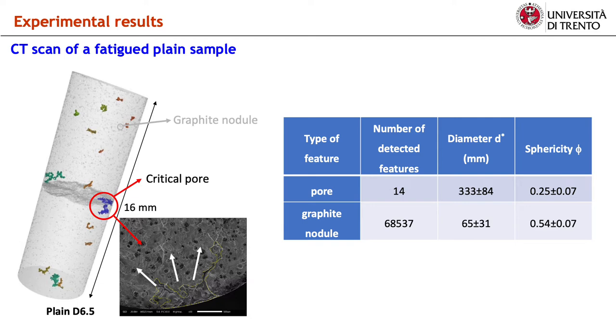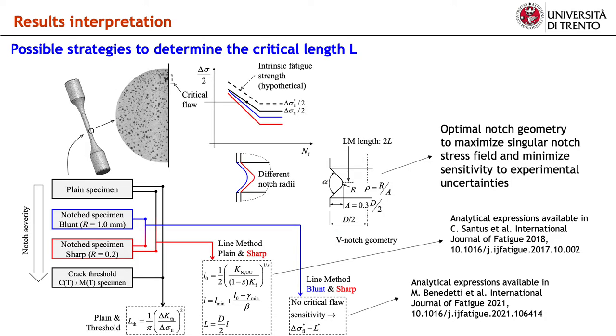It is now clear that the fatigue damage mechanisms prevailing in plain and notched components are different. This could hinder the applicability of the theory of critical distances, which postulates that the critical distance L can be inferred from a plain and a notched or cracked configuration.